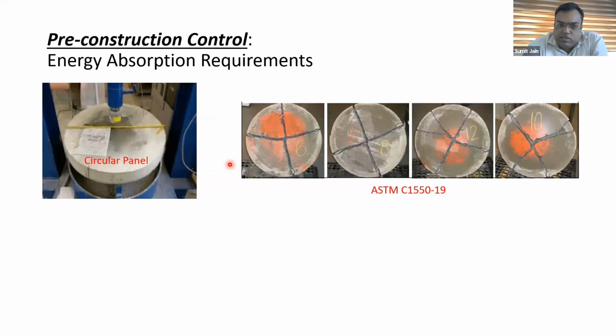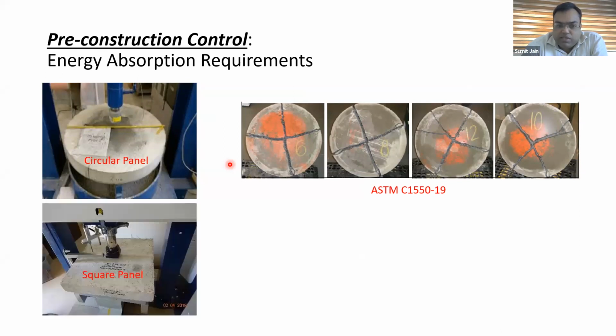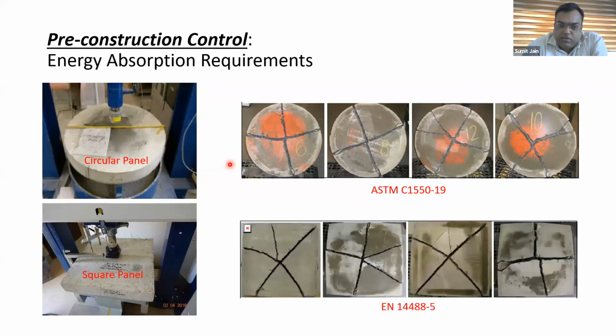As the load increases, the deflection occurs and the crack opens up, and the fibers which are joining the opposite sides of the crack come into action. Same test we can carry out on square panels. This is a test apparatus for square panels, and this is the European norm EN 14488-5, and these are the typical star cracks which we see in the square panels. Depending on the regulation, we can use either of the tests.